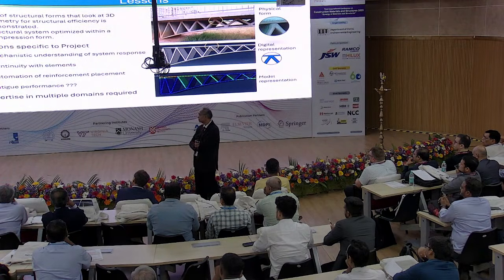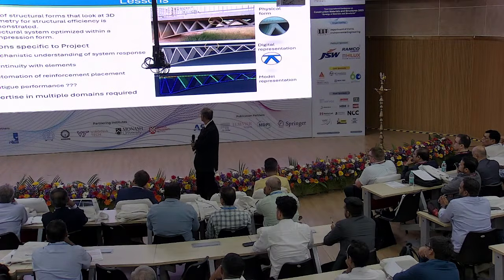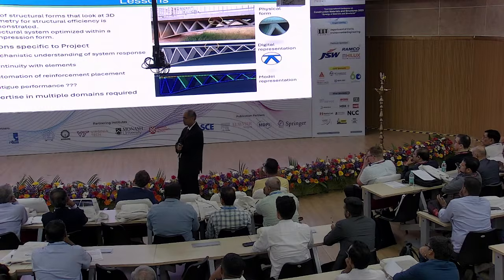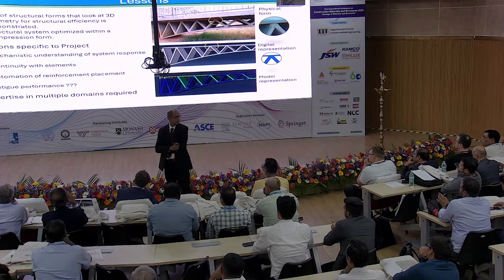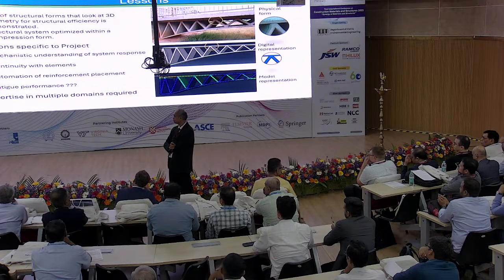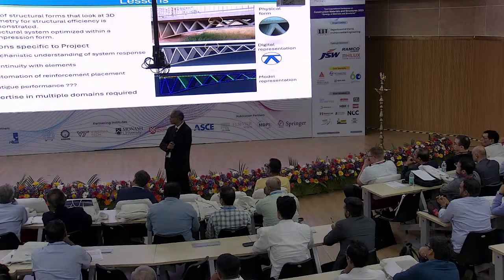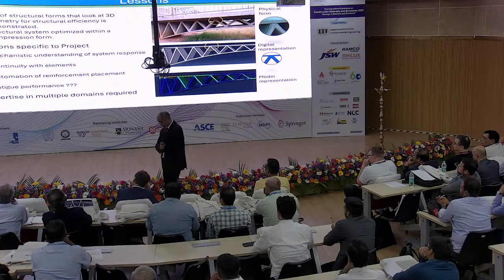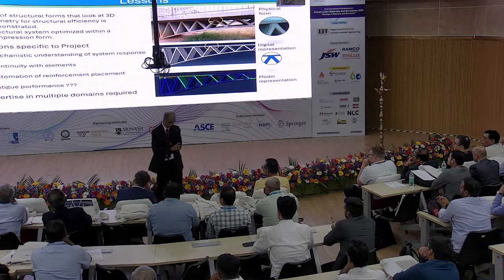What we have done is we do have a steel reinforcement that crosses over these two elements. So, if you look at my reinforcement template, that basically runs across the two diagonal members and goes into the top chord. So that gives me, it's almost like putting a shear stud across these two. So that's helping. What we've done is we have printed only these elements and tested them in different stress combinations. And we find that joint with that little bit of steel reinforcement going across is able to transfer the stress, and that doesn't fail.